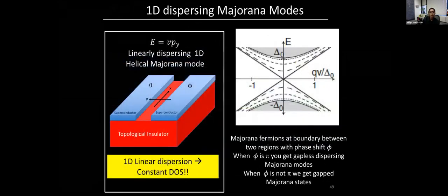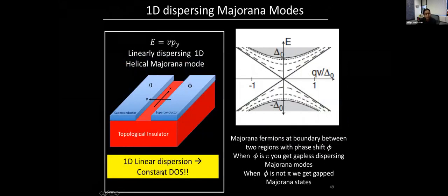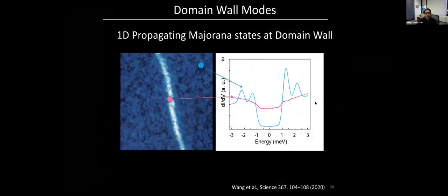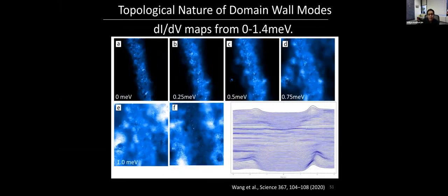Okay, so why do you get this flat density of states? Actually, the answer is quite simple. What is predicted in the system is that you should see linearly dispersing helical states inside the superconducting gap. And if you ask what is the density of states of a one-dimensional linearly dispersing mode, it's constant. So that's exactly why you see this constant density of states. This constant density of states represents a linearly dispersing mode living inside the superconducting gap.